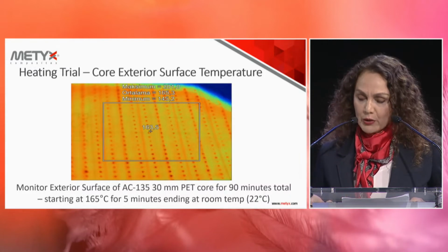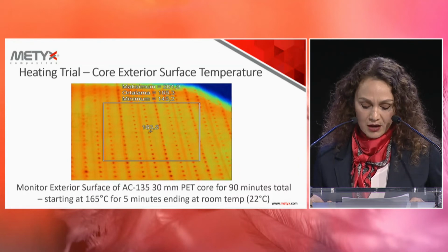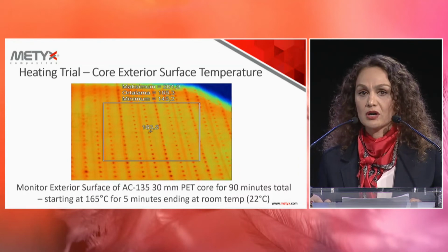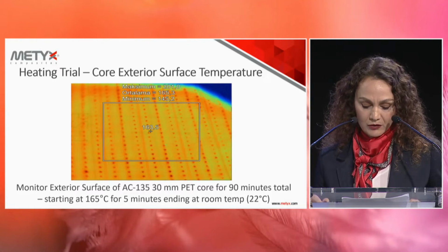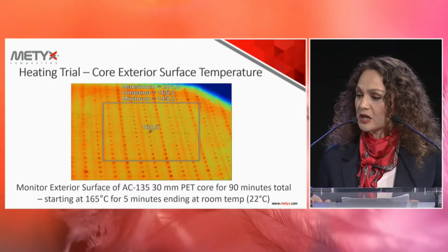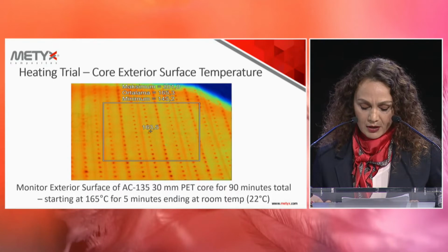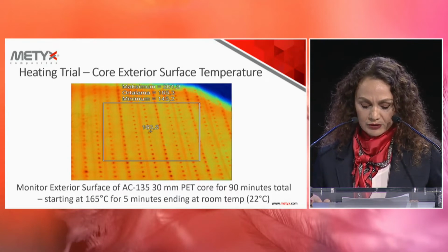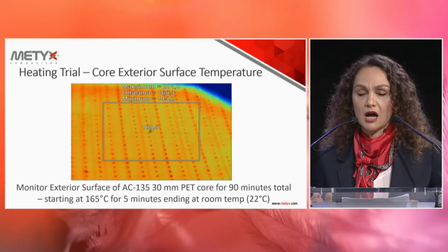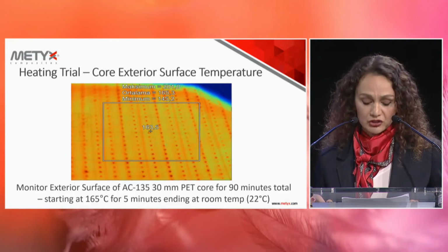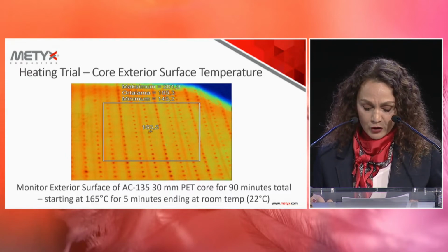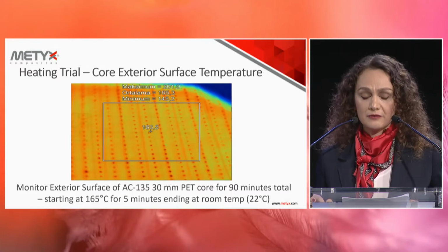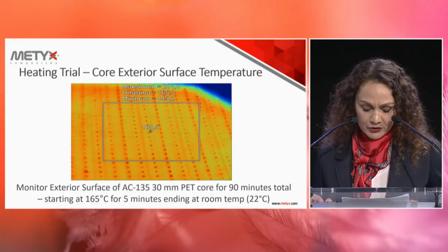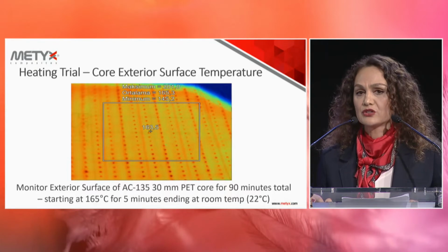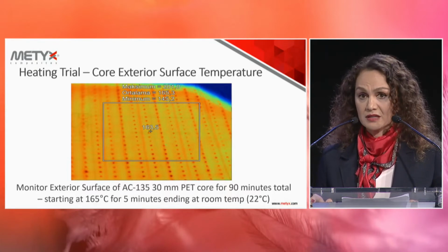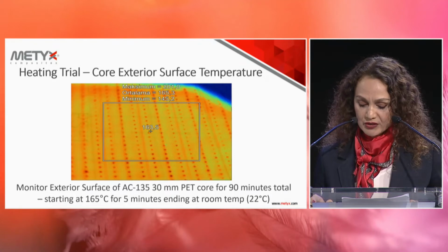For forming the core of spoiler parts, we need to understand how the core's performance is going to work under heat. What is the behavior of that? To do that, we measure external temperature core measurements using a traditional oven. We ramp up together, core and oven, to 165 degrees C. Then we let the foam sit in the oven at that temperature for 5 minutes, then pull it out and measure the surface temperature over 90 minutes to see the temperature changing on the surface.